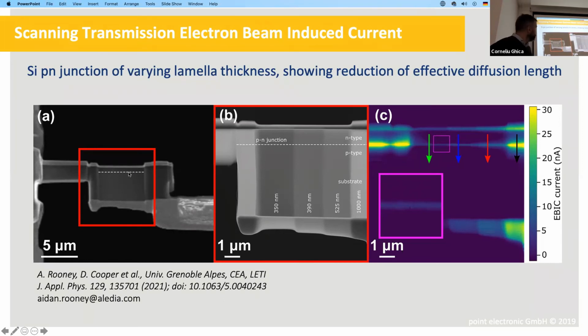It's a silicon PN junction, so we know what it is, and we know from the recipe of how this was made how deep the PN junction would be, so we know it's there. If you then take this to the TEM and do a HAADF signal, STEM image, you can see more details, and you can also see that this has been prepared at different thicknesses as a test device. We're going from something like 350 nanometers all the way up to 1 micron. So same material, same junction, different thicknesses.